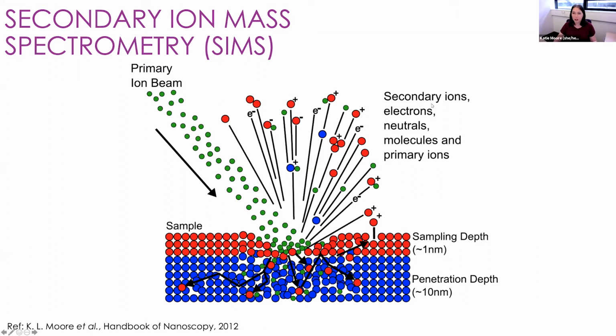So we collect those secondary ions and send them into a mass spectrometer, which allows us to analyze those elements according to their mass. Therefore, by scanning this primary ion beam over the sample surface, we can build up a chemical map of the elemental distribution inside our sample. It's worth noting as well that this really is a very surface sensitive technique. We're really only sampling the top few nanometers of our sample surface in this analysis.